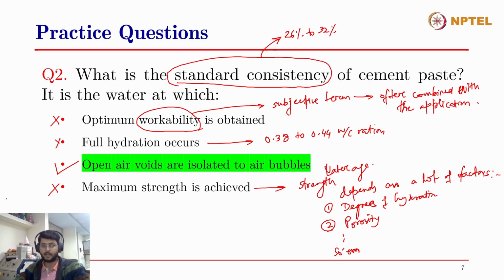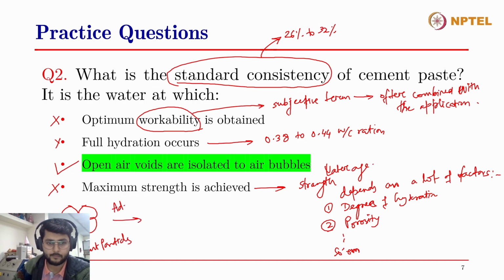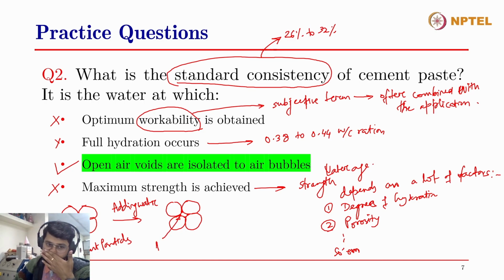The right answer is open air voids are isolated to air bubbles. So it was also shown to you in the lecture as well. Let's say these are the unhydrated cement particles inside a given matrix, and this used to be the air void. Upon adding water, what happens is this void trapped between these particles is slightly filled by water, while there is still air entrapped within the voids, and it is connected. The air voids are connected.